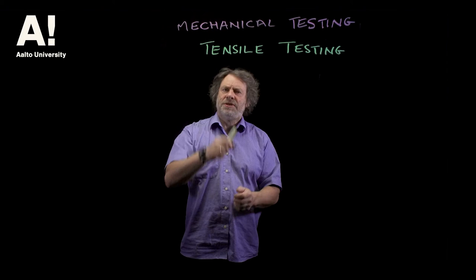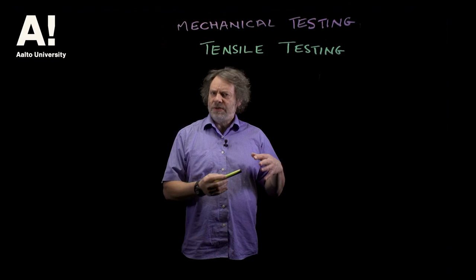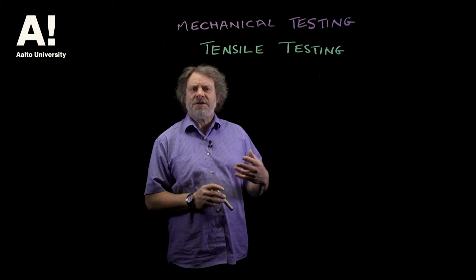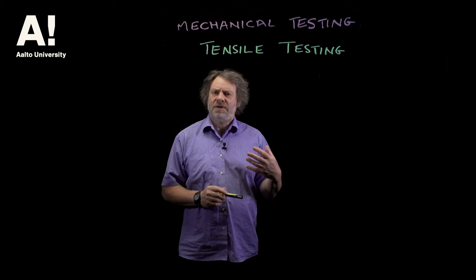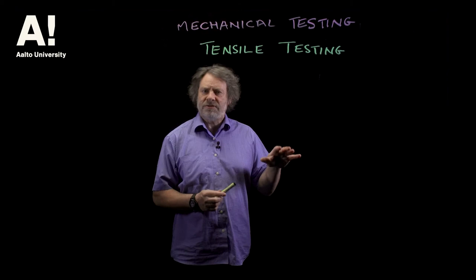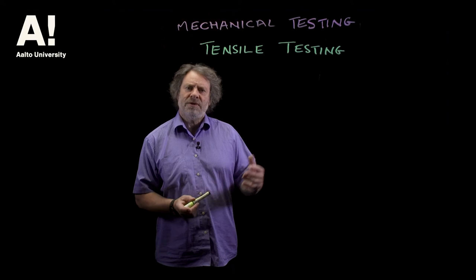With tensile testing, we obviously test a sample in tension. There are a number of things we need to be aware of before we do a tensile test or indeed any mechanical test, especially if we're working with a material like wood, which is a reactive material because it reacts to its environment. Before we test any piece of wood we have to go through a conditioning phase. The standards will tell you how to do this, but if you don't do it properly you'll end up with different results depending on what conditioning history you used to prepare the sample.